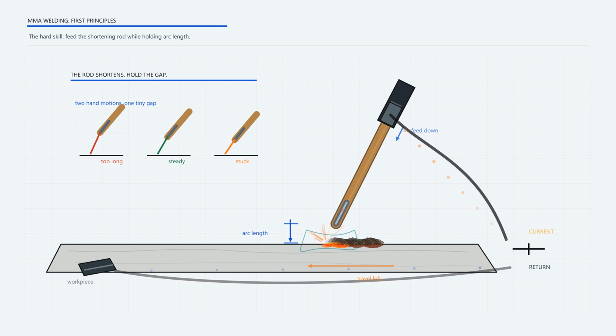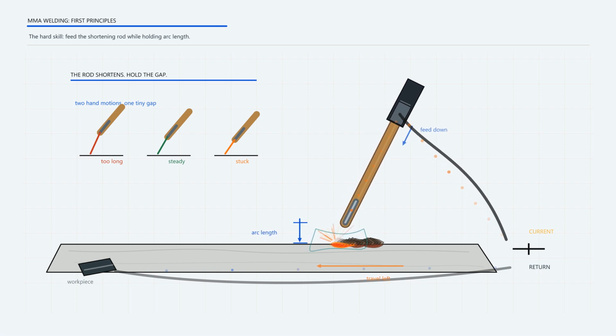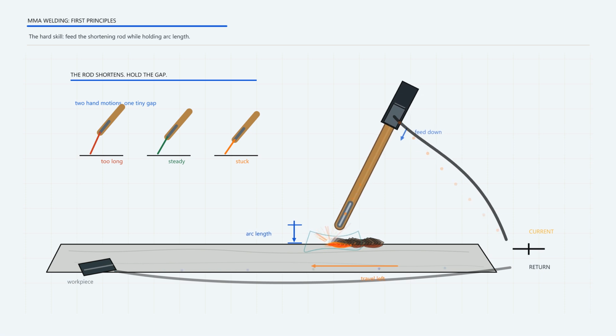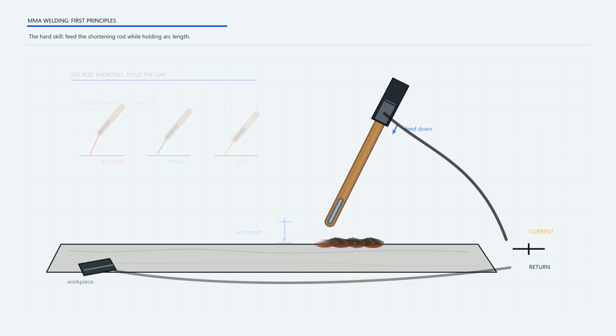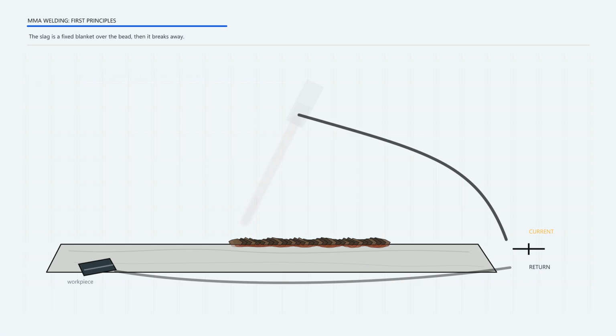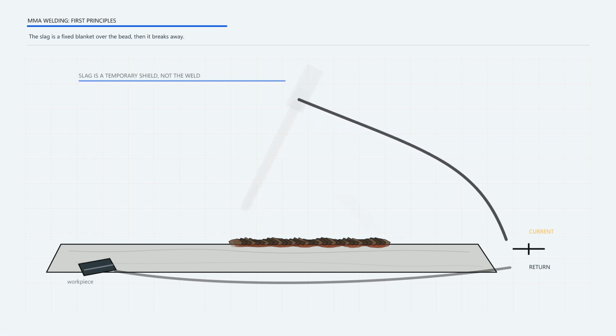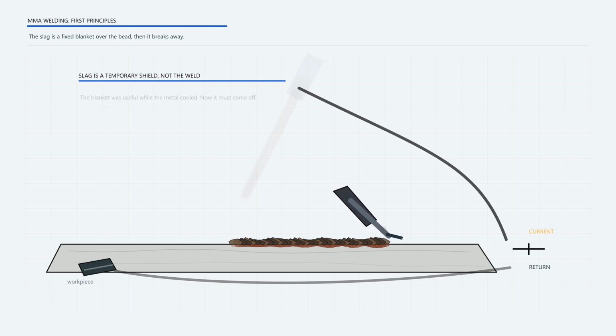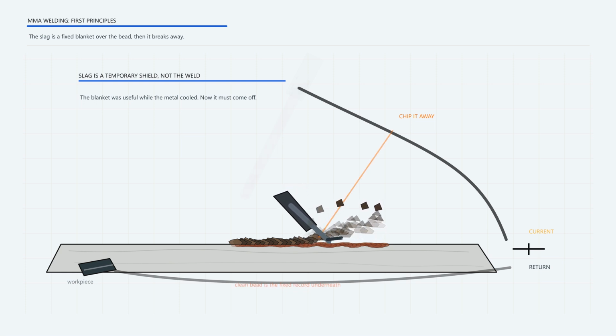After the bright part ends, the weld is not finished. The slag has done its protective job, so now it becomes something to remove and inspect. Chip it away and the bead underneath tells the story. A steady arc leaves a regular tied-in bead. A long arc leaves spatter and a rough profile. Too much drag or poor angle can let slag run ahead and become trapped in the weld. The bead is not just a line of metal. It is the frozen record of current, arc length, rod angle, travel speed, and slag control.